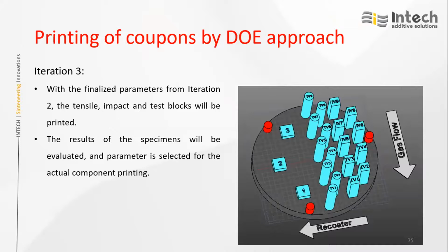In this test, 3 parameters, and we can see many tensile and impact coupons are there. If all 3 parameters are good, it's not that only one parameter set will work for the given material — there will be many parameter sets which will work for the material. The selection in this case again depends on the productivity.